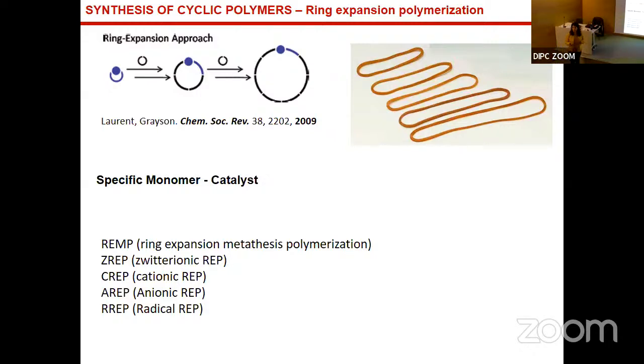Initially, the monomer or the catalyst can be cyclic. And then, upon certain conditions, the monomer starts to incorporate into this cyclic structure, and the ring is expanded, and forms the cyclic polymer, something like this. These are the typical polymerization techniques: ring expansion metathesis polymerization, zwitterionic, cationic, anionic, radical polymerization.